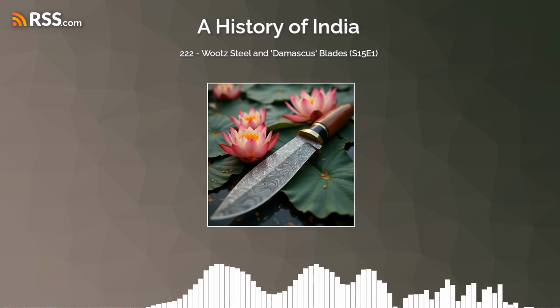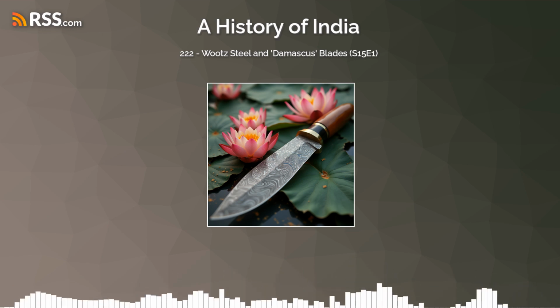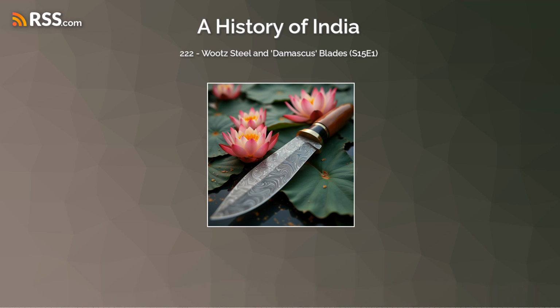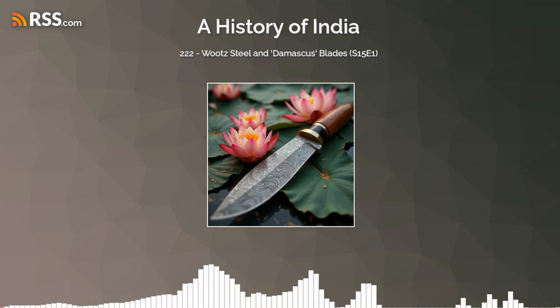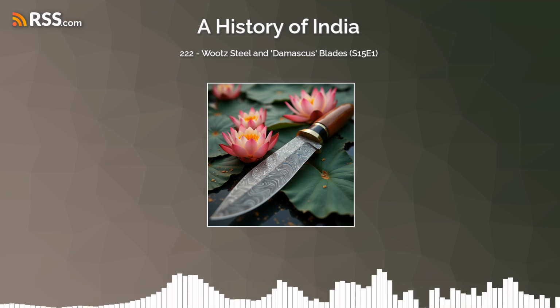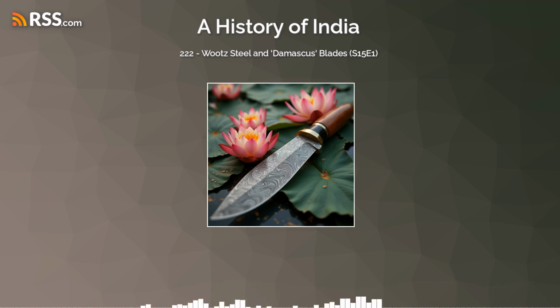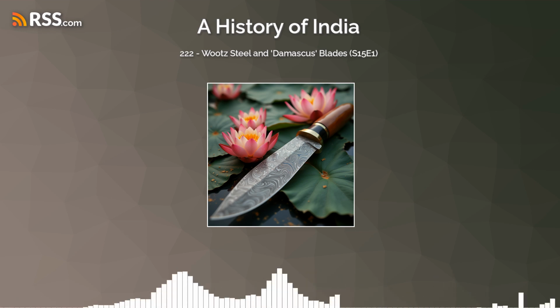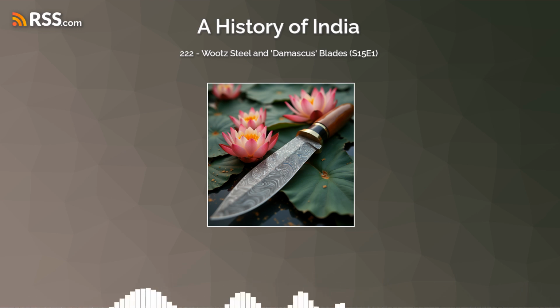Exactly. The forging was a precise thermal and mechanical process. It did more than just shape the blade. It fundamentally changed the microstructure inherited from the crucible. It took that potentially brittle cast structure and made it ductile and incredibly tough. It did this by changing the shape, the morphology of the cementite. Instead of maybe forming a brittle network along the grain boundaries, the careful hammering broke it up and either spheroidized it, turned the carbides into tiny rounded particles, or, crucially for the pattern, it aligned the carbides into those flowing bands we associate with Damascus steel. That alignment let the pattern pop when it was etched.